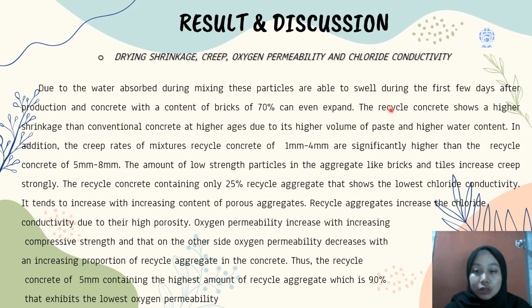The recycled concrete shows a higher shrinkage than conventional concrete at higher age due to its high volume of paste and higher water content. In addition, the creep rates of mixtures of recycled concrete of 1 mm to 4 mm are significantly higher than the recycled concrete of 5 mm to 8 mm. The amount of low-strength particles in the aggregate, like bricks and tiles, increases creep.